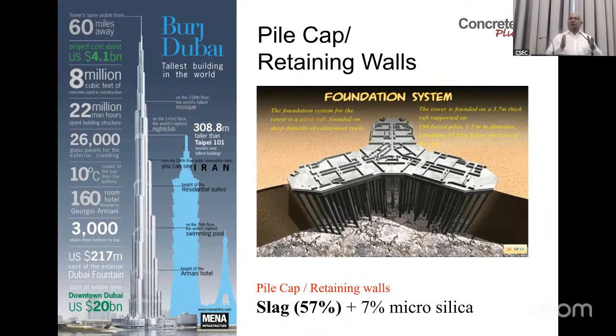The second thing is, if you use slag instead of fly ash, usually in general you have to use double the amount. Say if you use 25% fly ash for durability, in slag you have to go to 50%.